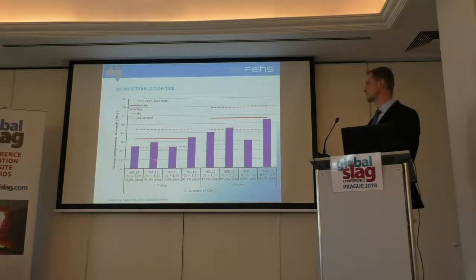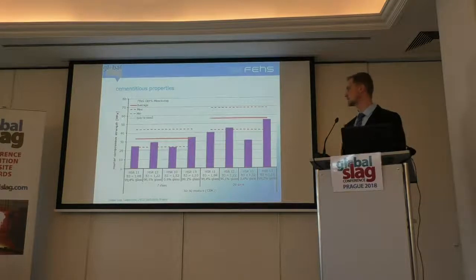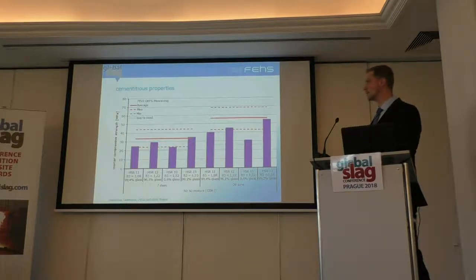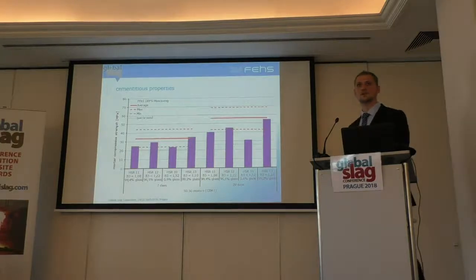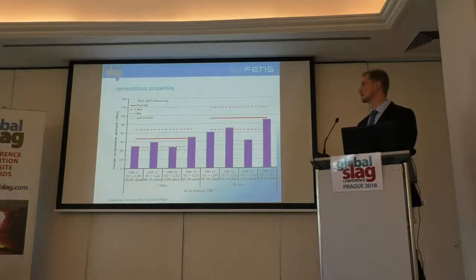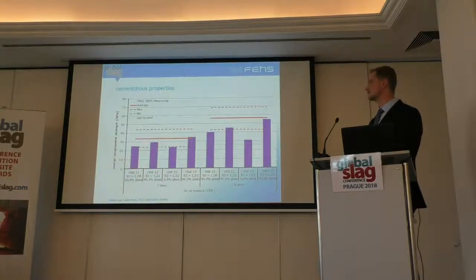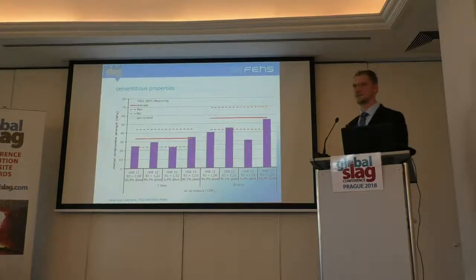The cementitious properties in the first step, we looked with a 50-50 mixture with a CEM I, okay, how are the compressive strengths of the mortar prisms. You can see here the FEhS monitoring, as my colleague Mr. Ehrenberg said before. That's a monitoring we are doing 2 times a year for every blast furnace of our member states. So we have a big database with the maximum and minimum compressive strength and an average. And here the green line is the quartz sand, so that is the 0 reference.